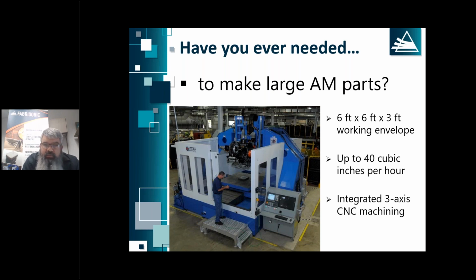From a deposition rate, when you look at some of the powder-based processes, you hear numbers of say 1 to 4 cubic inches an hour of volume. We're printing more on the order of 40 cubic inches an hour. So it's a little bit faster, but we would never call it fast. It is still a fairly slow process. Again, for many of our parts, we'll start with something that's already existing and add material to it, to kind of leverage that ability without having to spend the money to print the entire part. And again, most of our machines are CNC mills and typically 3-axis, although we've done a few customs that have a few more axes to them.